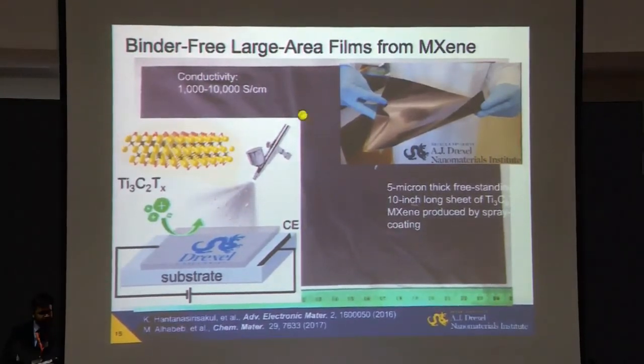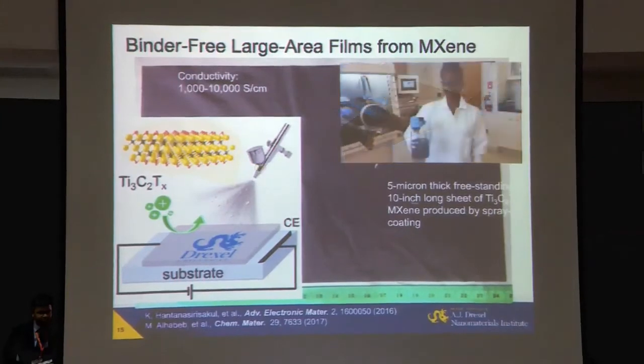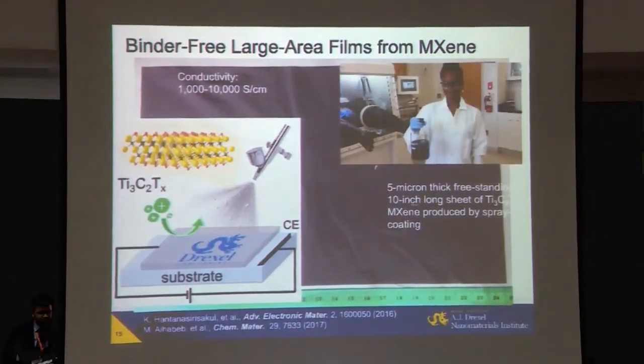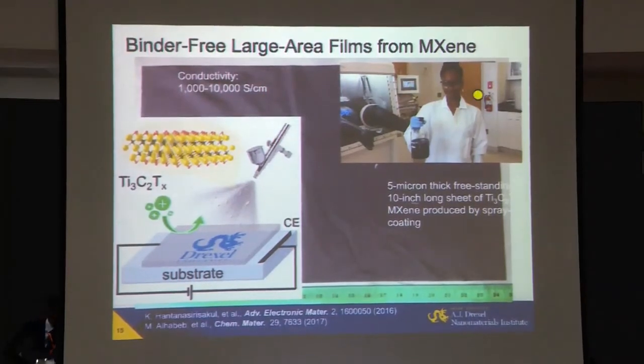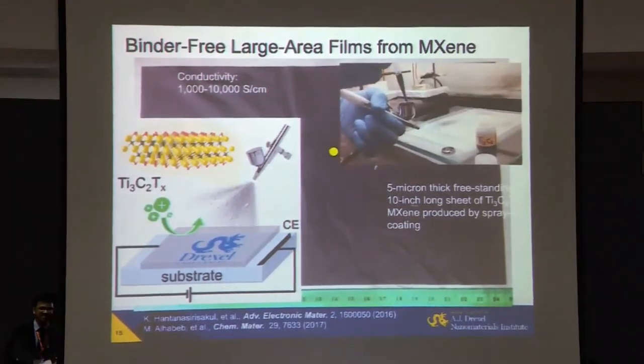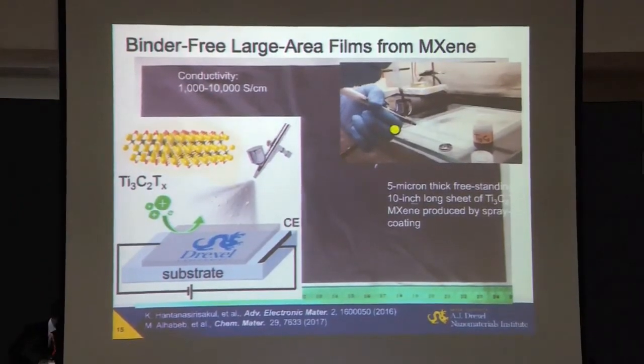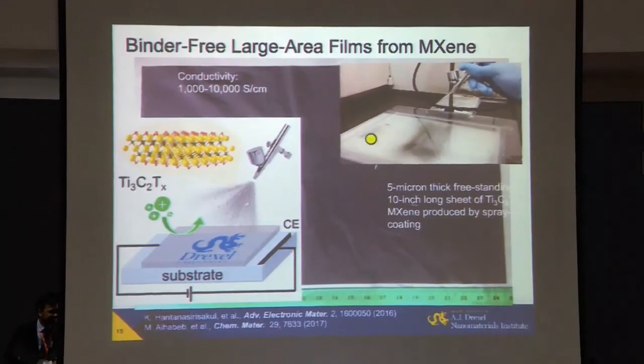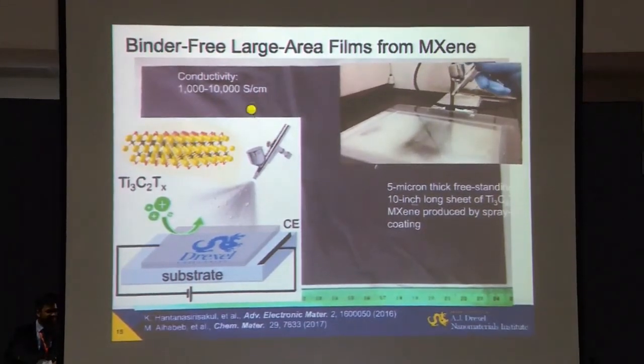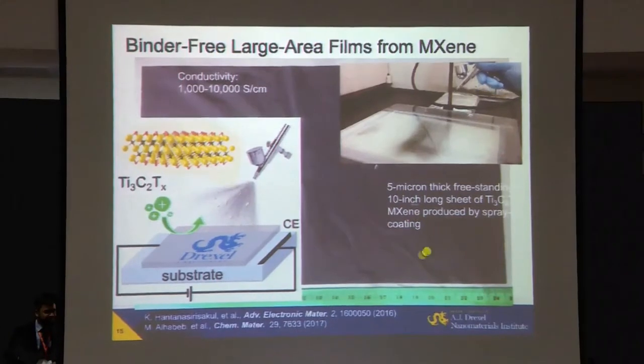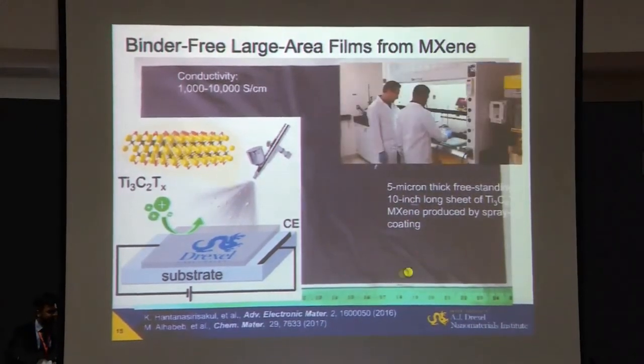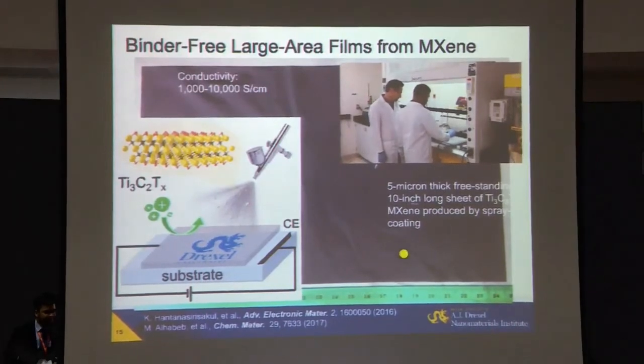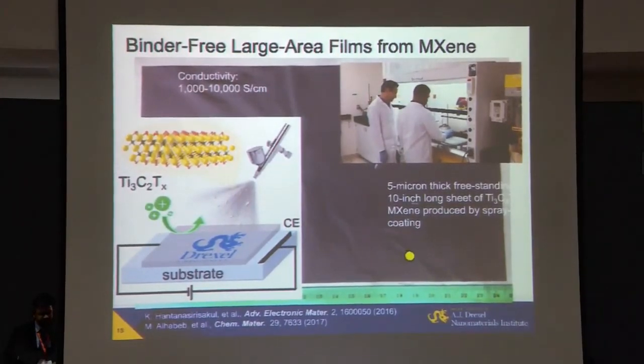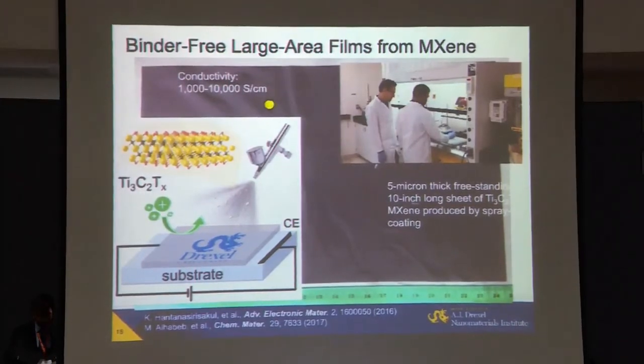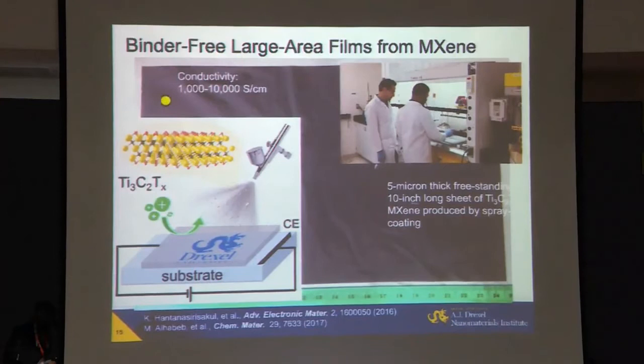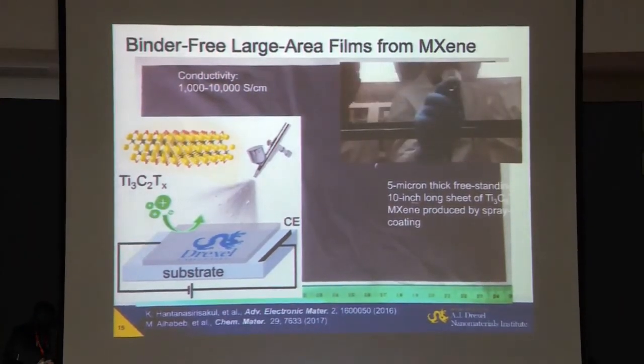My students bought for about $20 a spray gun for paint from a hardware store. This is one of my students holding a bottle with MXene solution. You see they're filling the spray gun and spraying it on the surface here. As a result of spraying, you can get this that you can see in the background, a sheet of MXene. This is actually MXene with graphene mixed for a composite material. You can see it's 5 microns thin, but you can see that it's freestanding and separated from the surface. And depending on the amount of graphene, in this case, we had about 1,000 to 10,000 Siemens per centimeter.